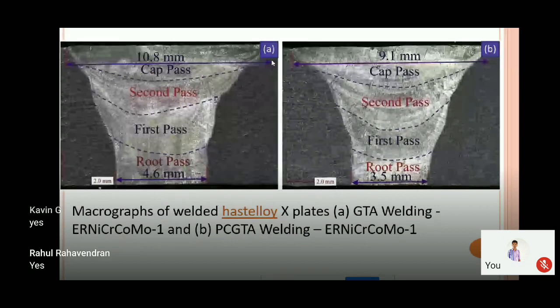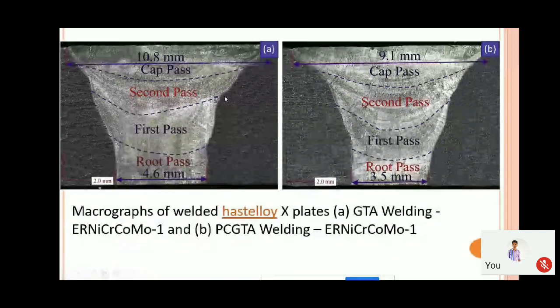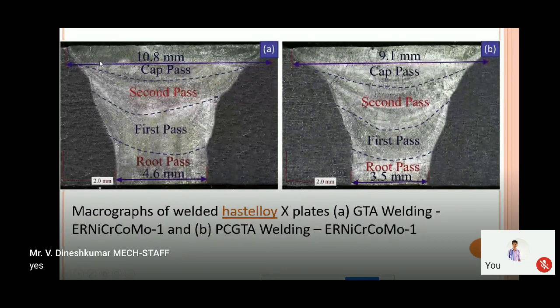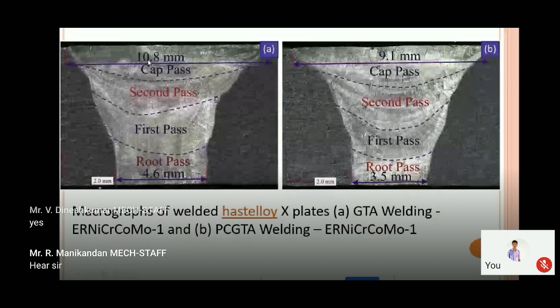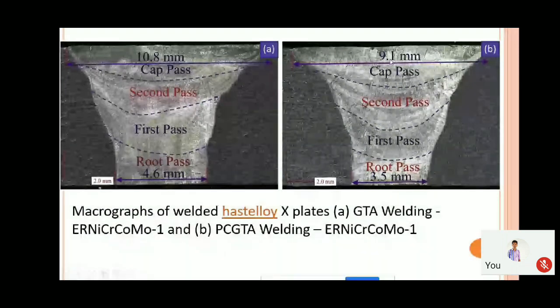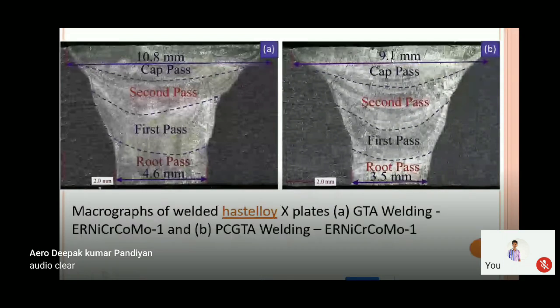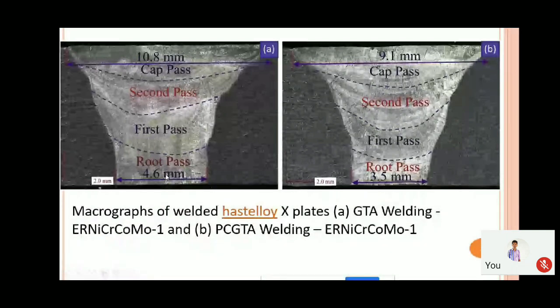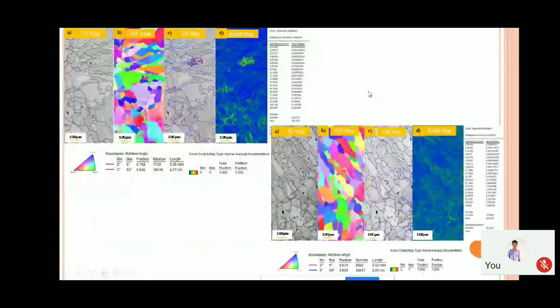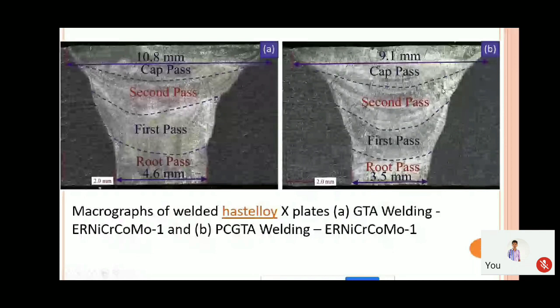So this is the macrograph of the cross section of the weldment. Now again, this is the GTA welding and this is the PCGTA welding process. Now you can see here the width of GTA is very high. Here it is about 10.8, whereas here it is 9.1. Almost more than 1 mm width is reducing. And similarly here you can see it is 3.5 mm, here it is 4.6. Also the structure of the weld bead is something different from this case, right? So when you are using the PCGTA mode of welding process, the width of the fusion joint also reduces.